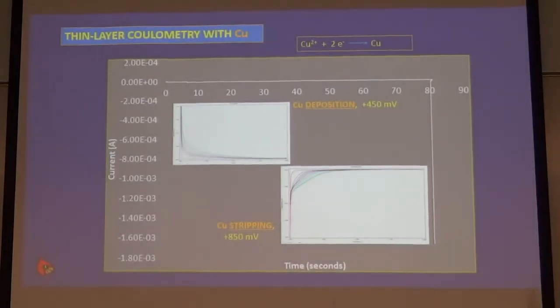So, beaming from our success with ferrocyanide, we decided to move not right to arsenic, but to something a little closer. We went to copper. Copper ions can be reduced to copper metal. So we decided to try the system out on something that's not so toxic. This shows results here. This is the current time curve. We fill our cell up with the copper ions and apply a potential to cause its reduction. Here we're looking at the current as a function of time. So we apply the potential, start the reduction here. The current spikes and then decreases over time. You can't begin to read that, but that's out at 1 or 2 minutes. You can see the current decreases and goes to the background.